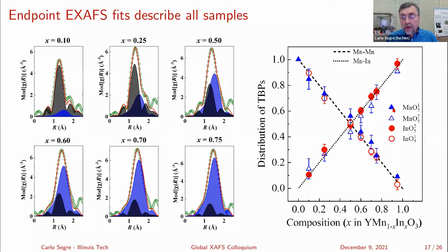And over here, you can see the results of these fits. The dark blue, or filled-in blue triangles, are the fraction of number 1, which is the blue color, and number 2, which is the black color. And similarly, number 1 of the indium and number 2 of the indium. As the amount of the dilute manganese environment drops linearly, then of course the amount of the concentrated indium goes up. So these 2 lie very nicely on lines that match up to each other. That is, the indium and the manganese give you the same results. And this is basically the same result we get from the XANES fitting. So it's all identical.